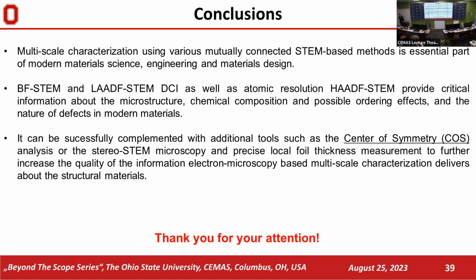So first, about this chemical ordering, this is very specific to this ordering, it's just this aluminum. Basically we found out empirically how we can see it and how we cannot see it, whether it's there or it's not there. If the superlattice spots appear, we are counting on the fact that we are just probing the volume, and it can be anywhere throughout the volume. And if it's there, it will pop up in the streaks. Obviously, we didn't do any thickness-based experiment, like how different it would be if we have 20 nanometers and 80 nanometers. That would be interesting to do, but it's definitely something to consider.